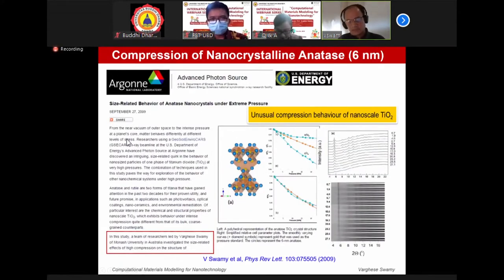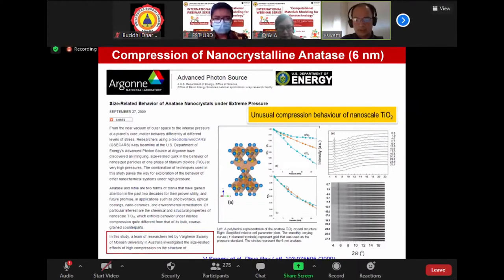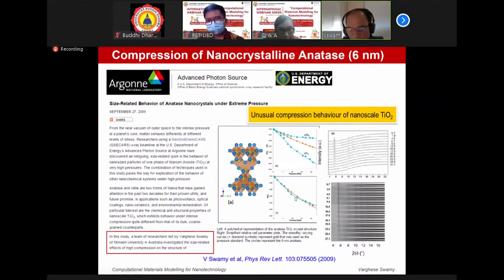If you analyze the compression data of 6 nanometer anatase up to about 30 GPa, what you see is that these are the cell parameters plotted as a function of pressure. The a parameter initially compresses, and at some point in pressure, about 12 GPa, it gets stiffer. That means it's harder to compress along this direction. Similarly for the c parameter also. So if you plot the volume, you can see that there's a sudden break in the compression curve. That means the material is stiffening. And this was at that time an interesting result, and the APS, the Advanced Photon Source, put this up as a science highlight on their website.